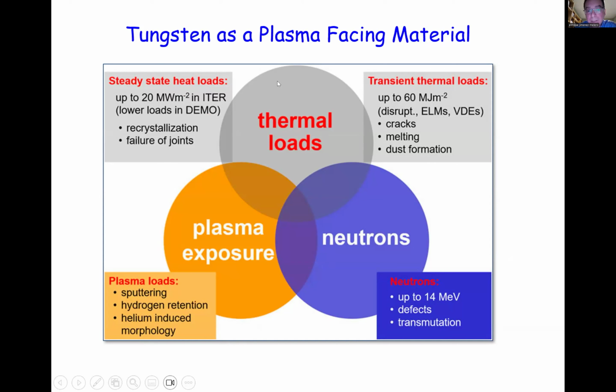reactor will be under thermal loads, both steady-state heat loads and transients, plasma exposures and neutrons from the reaction, and all those things is a cocktail that can generate a number of problems or challenges for tungsten, from recrystallization, failure of joints, cracks, melts, dust formation, sputtering of tungsten, hydrogen retention, deuterium and tritium as isotopes, and helium-induced morphology, and I will show you a few examples of this in a second. And neutrons, they have extremely high energies.